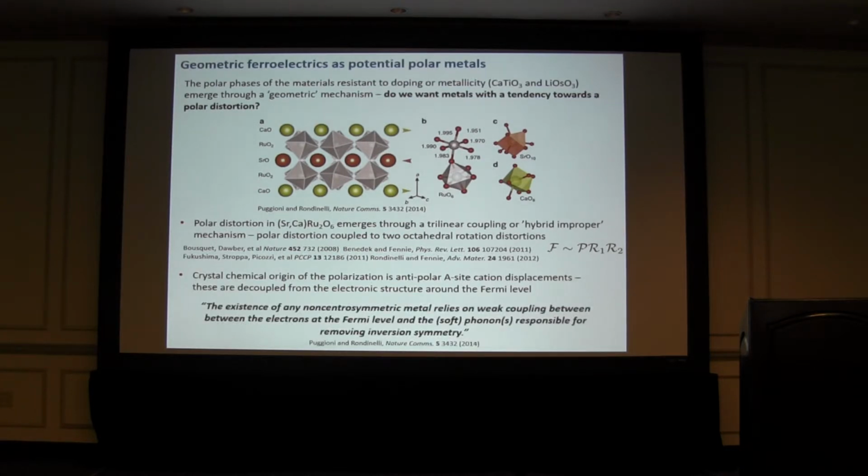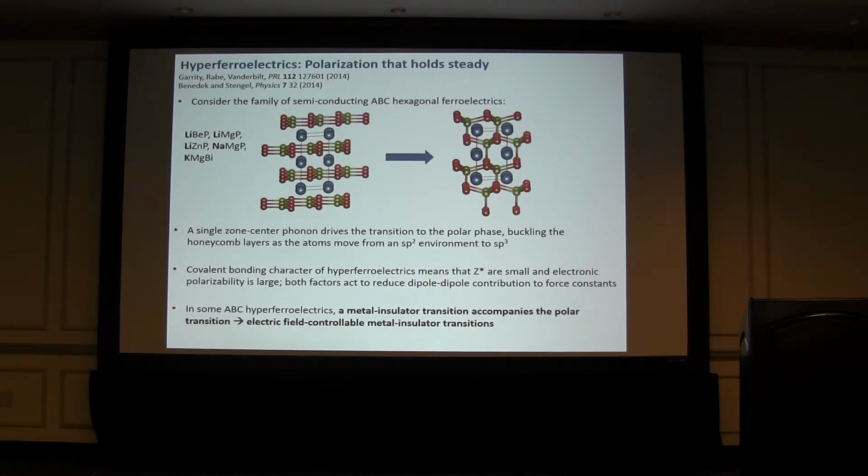But that doesn't always have to be true, so this is where I wanted to talk about this work. The Rutgers group recently wrote some very nice papers about this family of potential non-oxide semiconducting ferroelectrics that they describe as having a stuffed Wurtzite structure. The Wurtzite framework is given by these green and red atoms, and then these stuffing atoms are in blue or in bold over here.